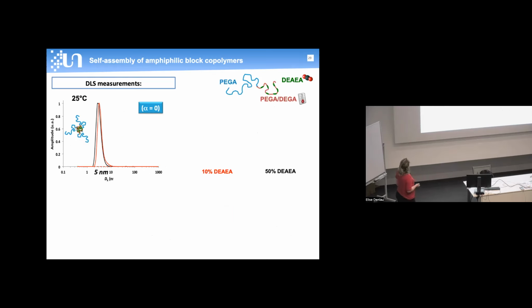So then we studied the characteristics of the polymer in water. First, we found by dynamic light scattering measurement that the objects formed at neutral ionization degree, at alpha equals 0, are about 5 nanometers, whatever the composition of the CO2 responsive unit.